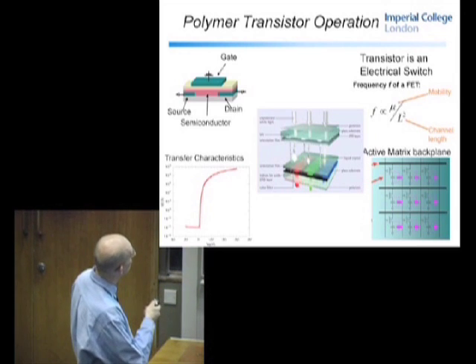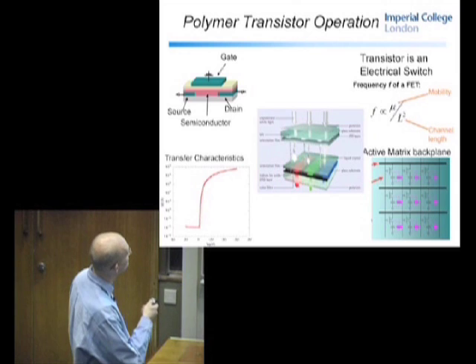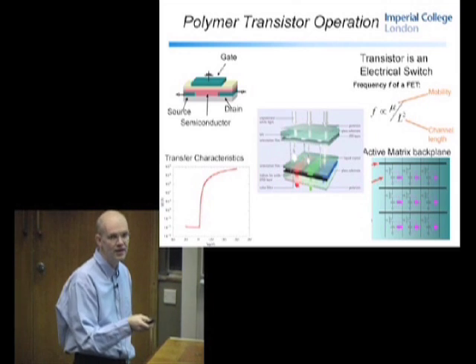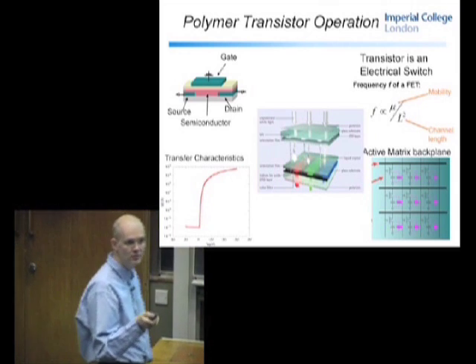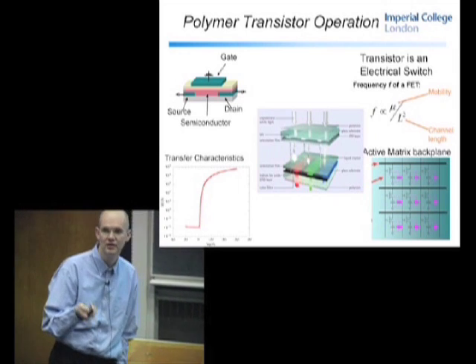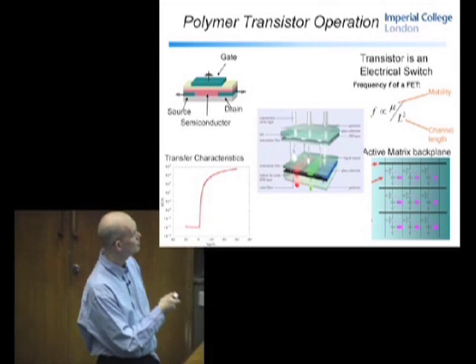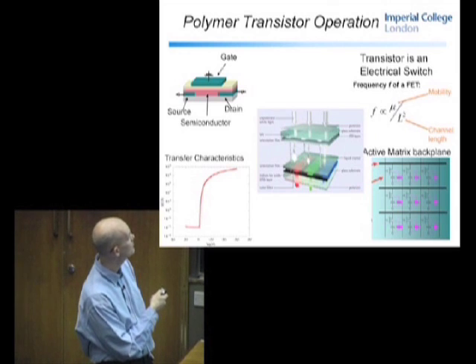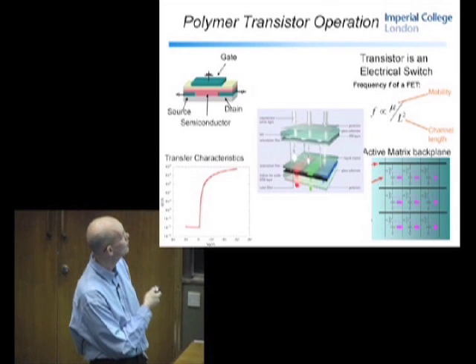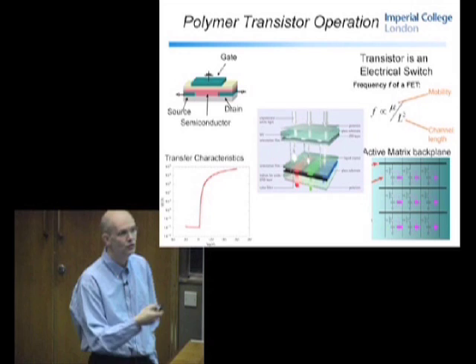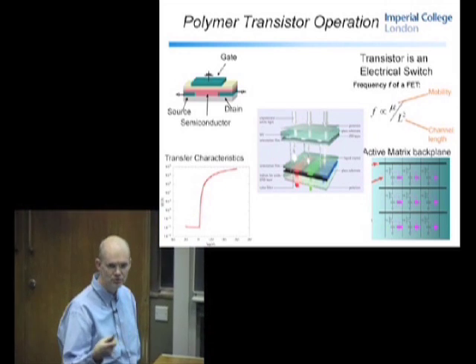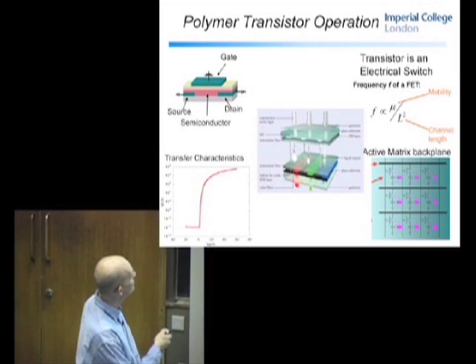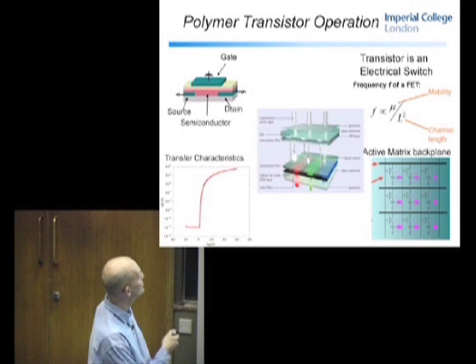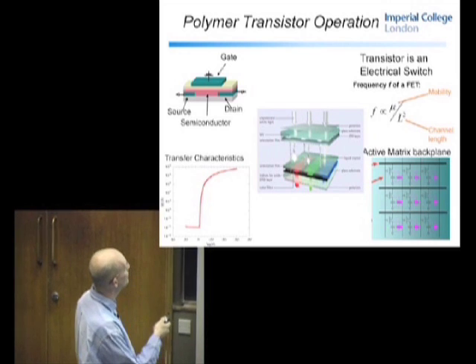On top of this you then deposit in red the semiconductor, and to give you a feel for the dimensions here, this is called the channel length, and this is typically about 1 to 10 microns in length, depending on the complexity and cost of your printing step. So if you use lithography, which is expensive, then you can get to very short channel lengths. And if you use something like gravure or flexo, which is much cheaper, higher throughput, you pay the penalty in resolution. You can only achieve maybe 50 micron channel length.